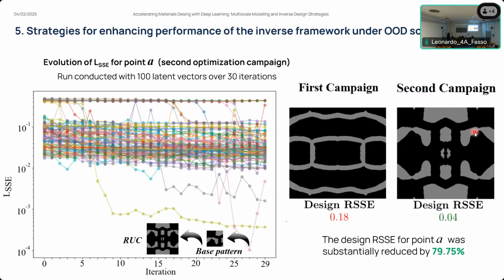We perform an extensive latent space exploration like this, as shown in this image here. Now we don't have just 10 latent vectors and 30 iterations. We allow 100 latent vectors for 30 iterations. And we observe already an important decrease in the error associated to the design. For example, we here compare the design that we obtained in the first optimization campaign and the one that we obtained for the same point A, out of these 4 points that I identified in the previous slide. And we obtained a reduction of the error by approximately 80%.